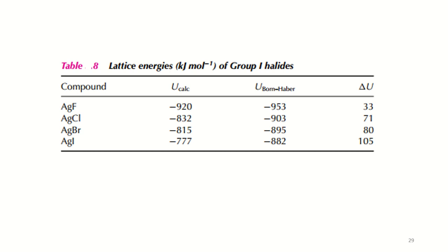Silver iodide is quite different, however. It is polymeric and polymorphic, and exists in at least three structure types, all of which have low coordination numbers, usually 4. Changes in the structure and coordination numbers due to increased covalent bonding are described later. I will discuss this at the end of the lecture.